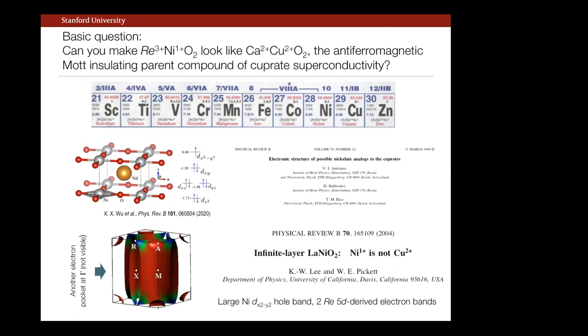So I'll come back to this point later, but if we take the LDA, the uncorrelated band structure limit of these compounds, there's pretty good convergence nowadays. But the electronic structure looks something like this. These large hole-like pockets are very reminiscent of the dx² - y² hole pocket in the cuprates. But in addition, there are two small electron pockets, here in the corner, and one you can't see in the zone center, that have a few percent of the electron density hosted in them. So that is one of the aspects that this paper is emphasizing.